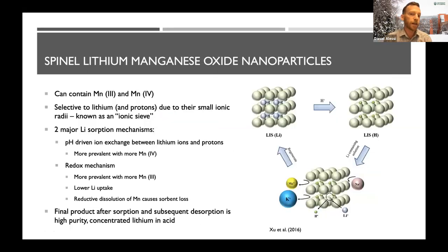There are a lot of options in these ion exchange materials, these DLE materials, and they tend to be metal oxide minerals. So titanium dioxide, manganese oxides, even relatively, I would say, exotic metals like antimony have been tested. But among the most promising out there, if you start looking at patents of companies, are what are called spinel lithium manganese oxide nanoparticles. And this is what we worked on for a few years.